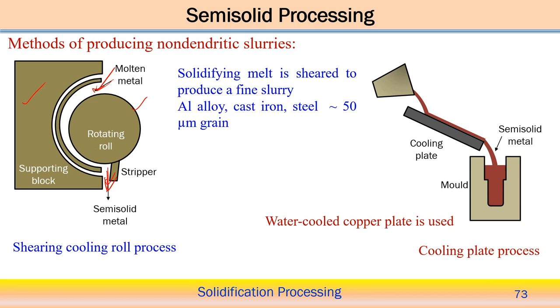Here the solidifying melt is sheared to produce a very fine slurry in aluminium alloy, cast iron and steel. This kind of metal is usually processed using this process, and a grain size of around 50 micrometers is possible to achieve.